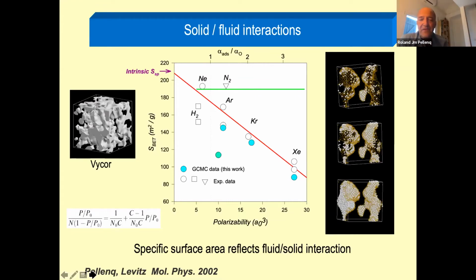Argon wets the surface, meaning it wants to cover all of it—it likes going to the adsorbent so much that it actually covers the surface. Not the case for xenon, not because xenon doesn't like silica, but because xenon likes other xenon atoms more than silica. So xenon produces small, nano droplets in the curvature of the surface without covering it homogeneously.